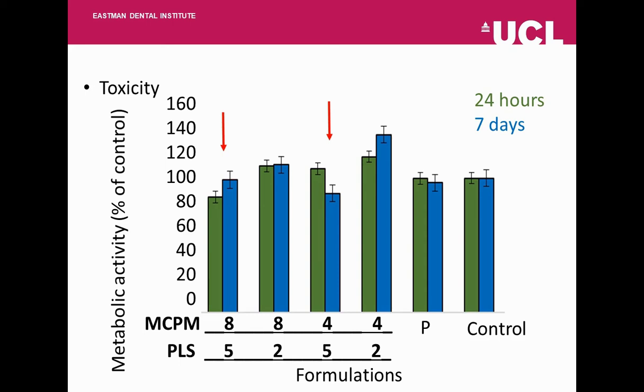So on this graph here, we can see the metabolic activity of the cells based on what they were exposed to. The first two groups are the high levels of monocalcium phosphate with varying levels of polylysine, 5 and 2, and then the next two groups with 4% levels of monocalcium phosphate with varying levels of polylysine. And then the last two are the extracts from the commercial PMMA and a control well. We can see at 24 hours and 7 days how the cells responded. The extract was collected after 24 hours and 7 days, so two different types of extracts the cells were exposed to.